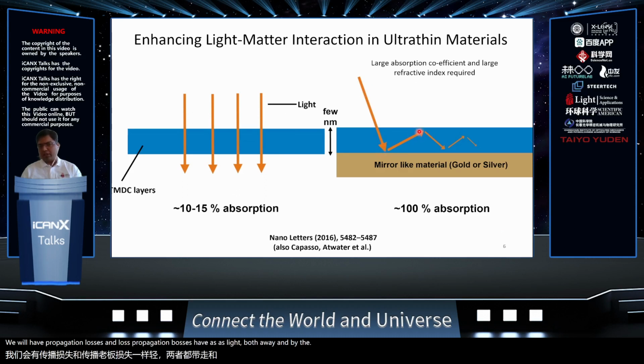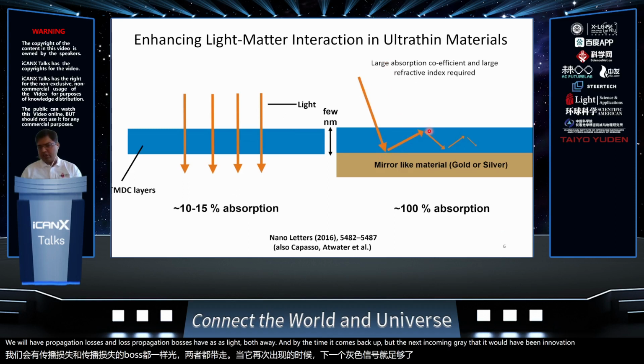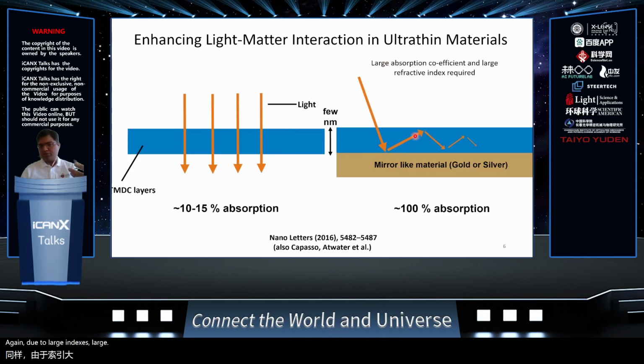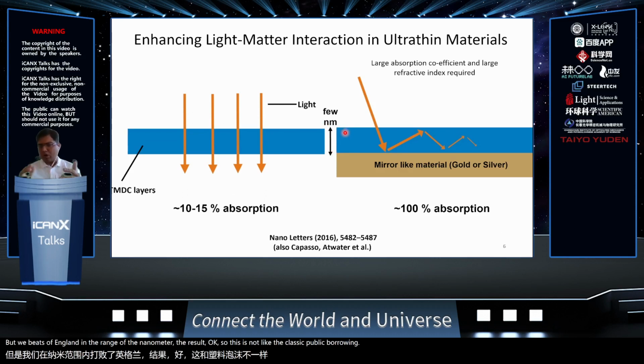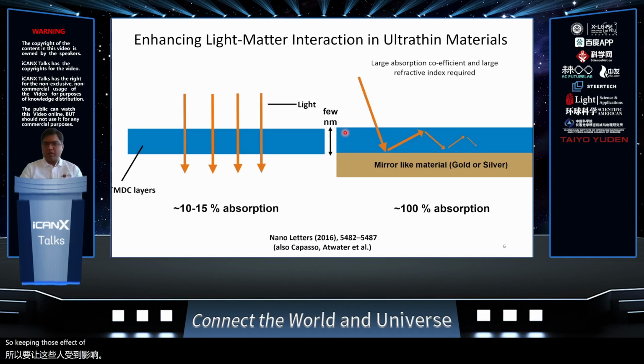And by the time it comes back up with the next incoming ray, there would have been enough phase shift, again due to large index and large absorption, that you could have destructive interference here, leading to near-perfect absorption. Again, I should mention here that this thickness is not lambda over 4n. It's actually deep subwavelength, in the range of 10 nanometers or so. So this is not like the classic Fabry-Perot. It's more like a lossy Fabry-Perot, if you will. So keeping this effect in mind, we wanted to explore if you can actually couple photons very strongly with excitons in this media.